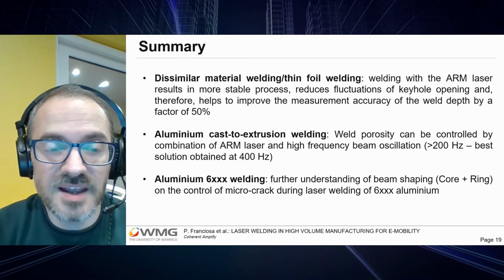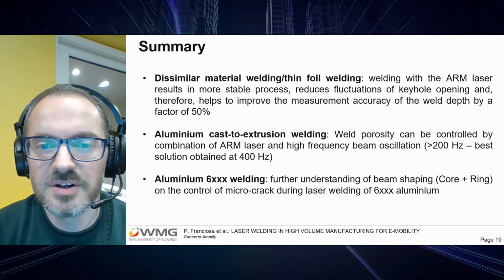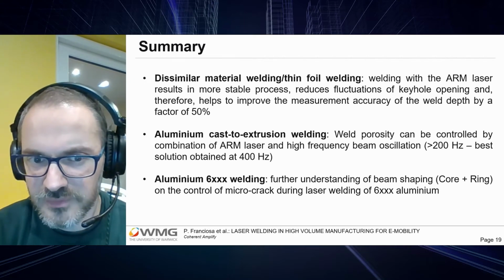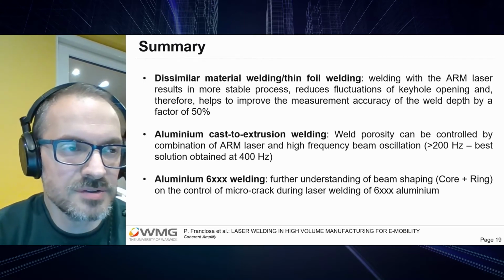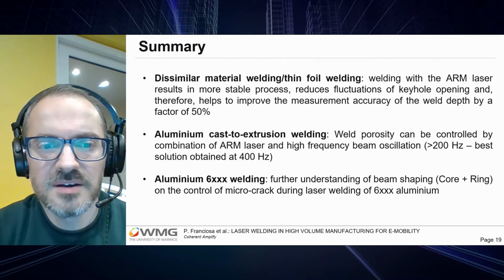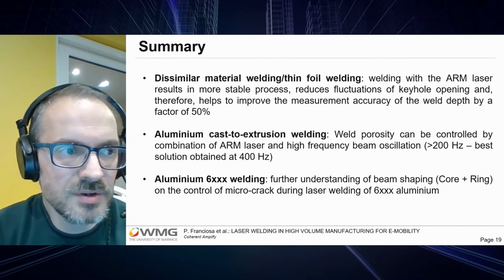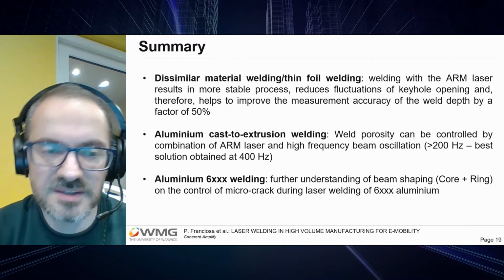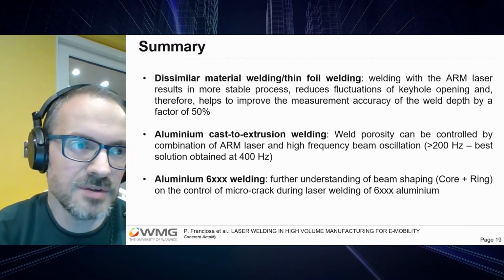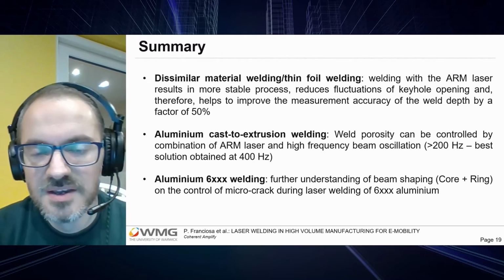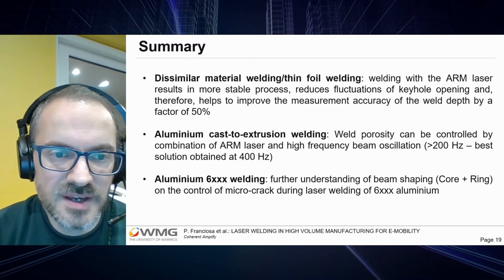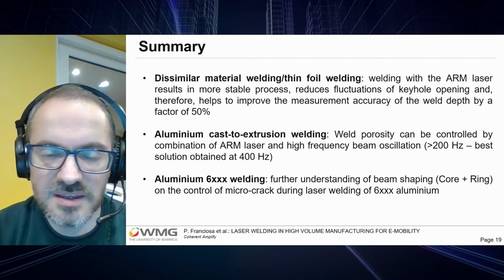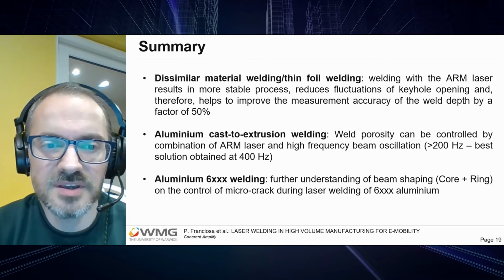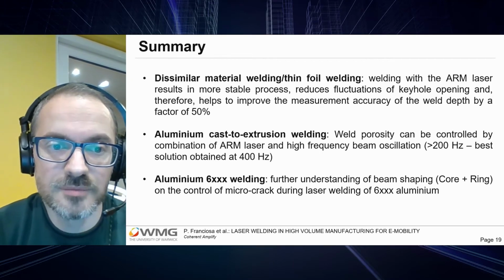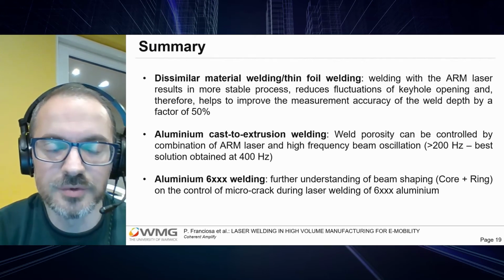The last application was about cast to extrusion, where the challenge was about the control of the porosity. And what we have concluded is by controlling the joint effect between the scanning frequency, so we are talking about using a wobbling head or oscillating laser beam, and the ring power, we achieved almost zero porosity within the molten pool, let's say within the weld.